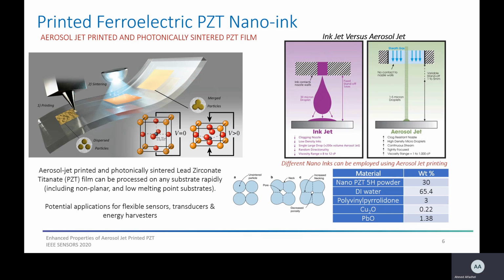So in this work, a photonic sintering method was presented by using repetitive high-intensity sub-millisecond flash pulses on an aerosol jet printed lead zirconate titanate, or PZT, nano-ink, to achieve high-quality sintered devices. The rapid processing results in enhancing the piezoelectric properties compared to the conventional thermal sintering process. The presented process allows the realization of high-performance, fully printed, flexible piezoelectric sensors on temperature-sensitive substrates for several applications.